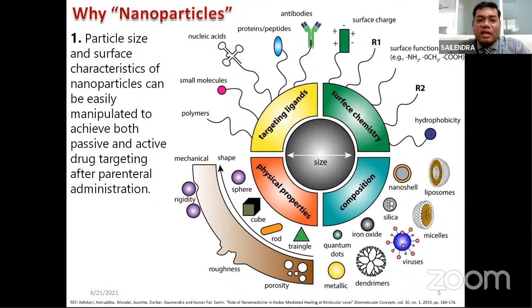Now, whenever we say nanoparticle, we have already defined the size at around 1 to 100 nanometers. Within this 1 to 100 nanometer range, we can have different shapes and sizes. It may be a spherical nanoparticle, a cubical nanoparticle, a rod-shaped nanoparticle, or a triangular nanoparticle. Not only that, there may be surface rigidity. That means your particle is very rigid in structure, not easy to degrade. There may be roughness on the surface of the nanoparticle. Again, that may lead to toxicity.